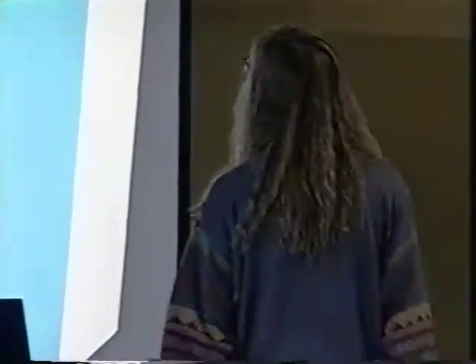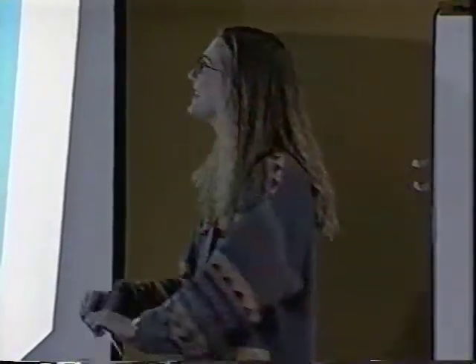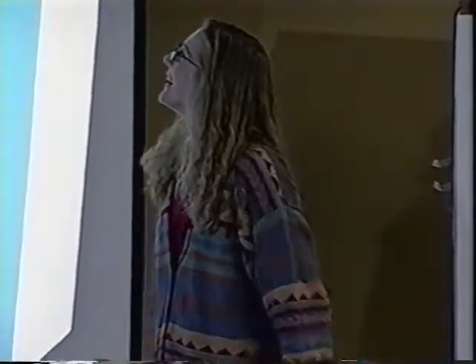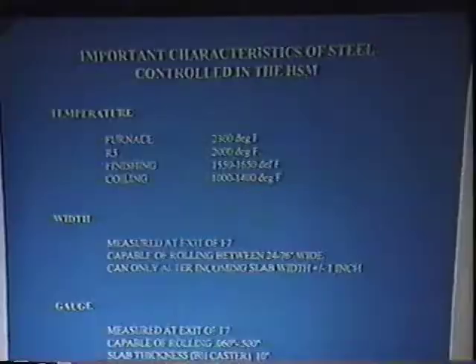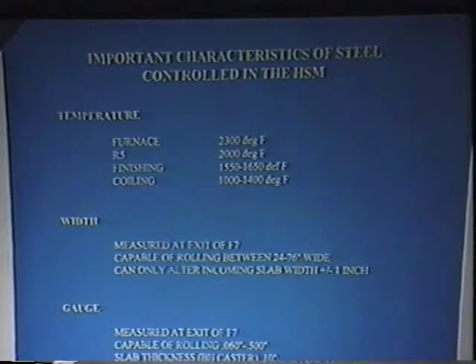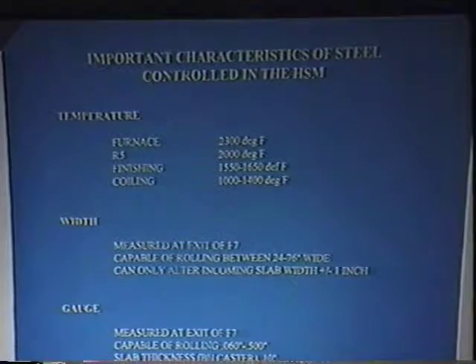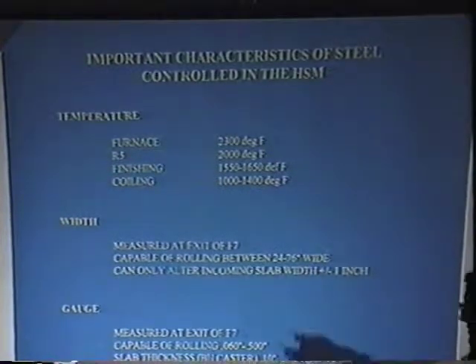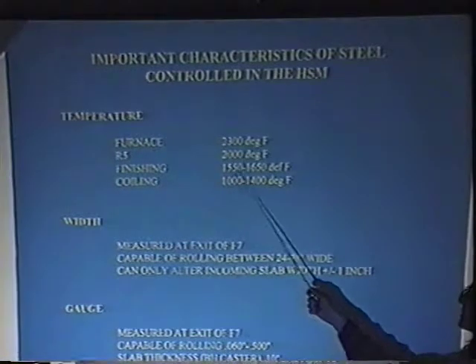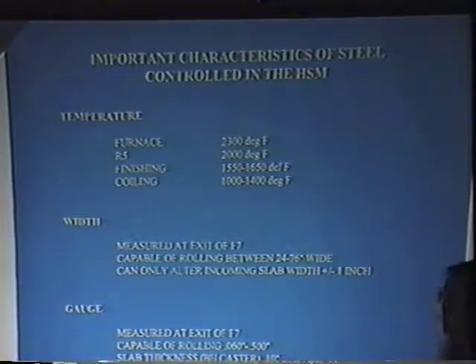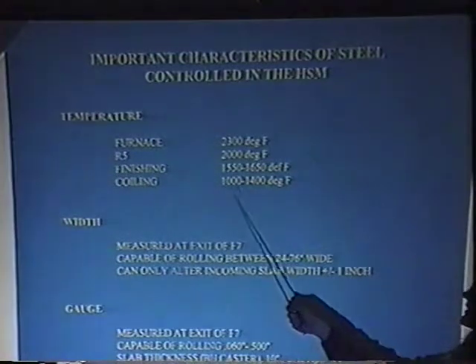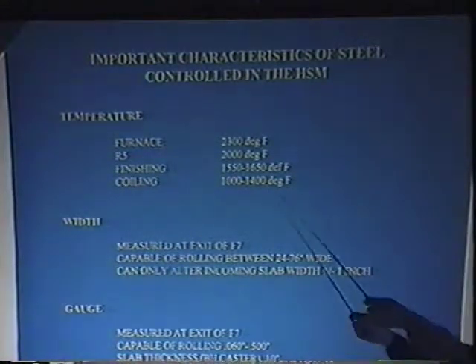Okay. Now this is dry, but we got to talk about it. My boss says, here's the presentation. Okay, I'll work with it. The title: Important Characteristics of Steel Controlled in the Hot Strip Mill. And this is just kind of a summary of what I've said before. The furnaces are 2,300 degrees. There's that number again. The temperature coming out of the last roughing stand, R5, is about 2,000. We finish between 1550 and 1650 degrees. And coil, usually around 1,000 to 1,400. Coils are really spongy when they're this hot.